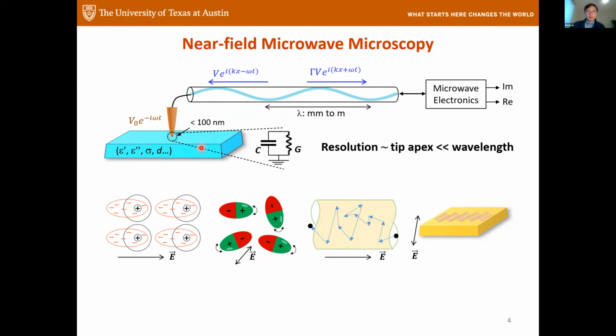So this is again just a guidance of what you would expect. As we turn on the backgate voltage, we're going to essentially increase the bulk sheet conductance. And during this process, we should expect that the imaginary part, which is the capacitance, increases monotonically, and the real part, the resistance or the loss part, increases up to a peak and then drops back down. So this is essentially just how the electric fields distribute between the tip and the MoS2.